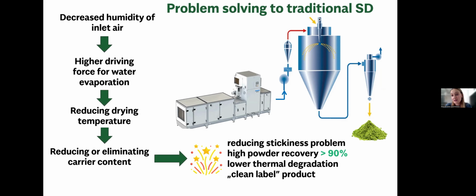With lowering drying air temperature, we can as well observe lower thermal degradation of bioactive compounds, which are quite present in the materials that we are working with. So fruit juices, vegetable juices, concentrates, etc. And as well, by lowering the carrier content or removing it completely, we can propose to consumers clean label products. And they are right now quite interested in these types of products, as they have more knowledge, the consumers, and they are really paying attention to what is in the formulation of the final product.